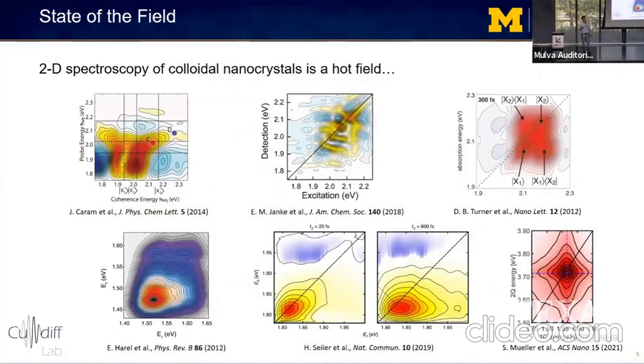So of course, 2D spectroscopy of colloidal nanocrystals isn't a new idea and has been done by many different groups around the world to reveal all sorts of interesting physics. But almost all of these studies have been performed at room temperature. And the issue with room temperature spectra is that peaks are severely affected by thermal line broadening, to the point where homogeneous line widths are often comparable to the inhomogeneous line widths.